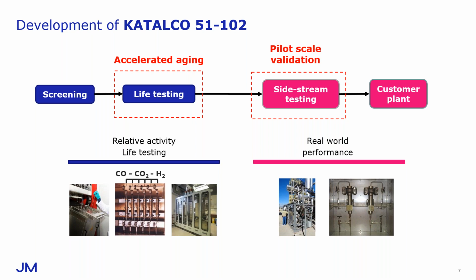Now, having used the accelerated aging microreactor to identify interesting candidate formulations, the next important step towards commercialization was to validate the performance of the formulations under real-world conditions. And to do this, we used a pilot-scale side stream unit placed at one of our customers' sites. And we are extremely grateful to Proman USA and their Pampa facility for hosting and operating this unit. So having subsequently successfully validated the performance of the new formulation that became 51-102 on the side stream unit, we then looked for opportunities to place commercial scale charges of catalyst with customers. And again, the first opportunity that arose for us was with Proman again, and also at the Pampa site.